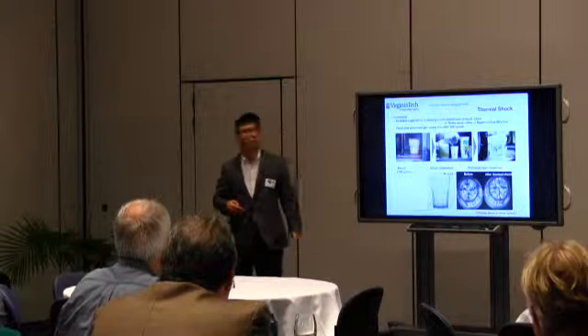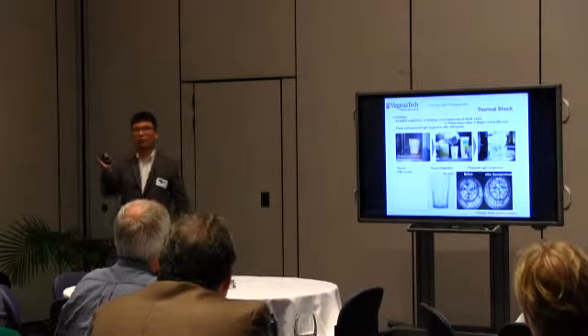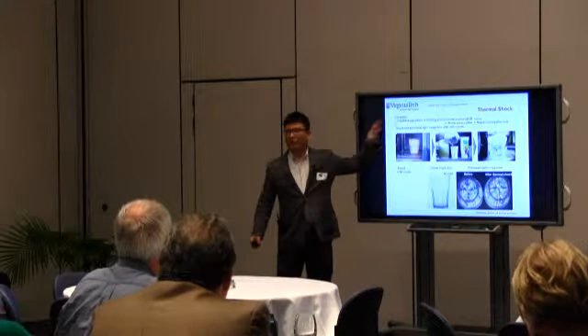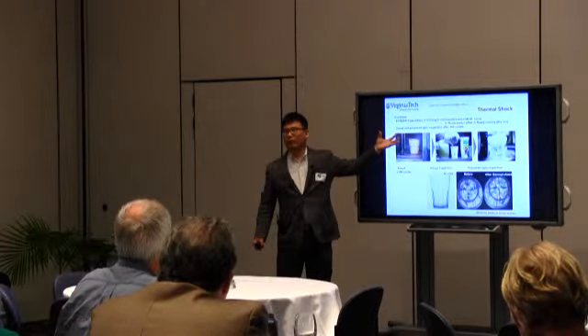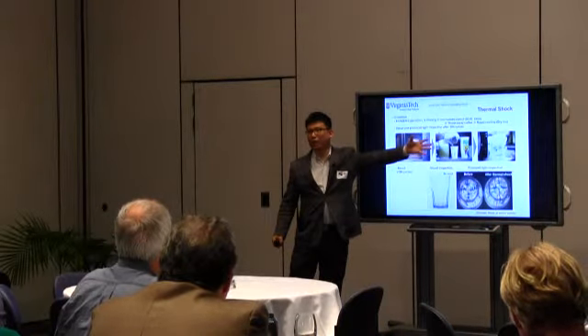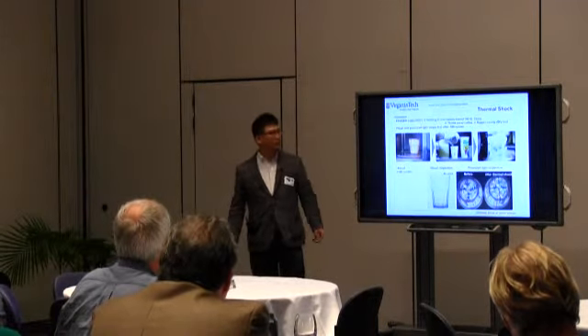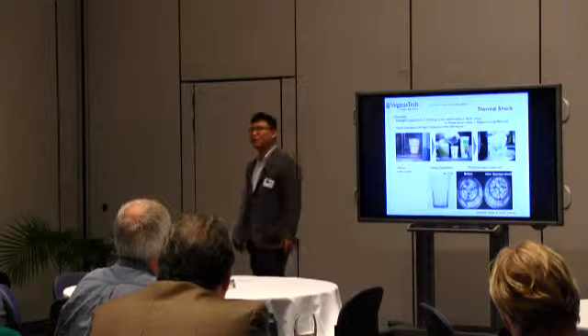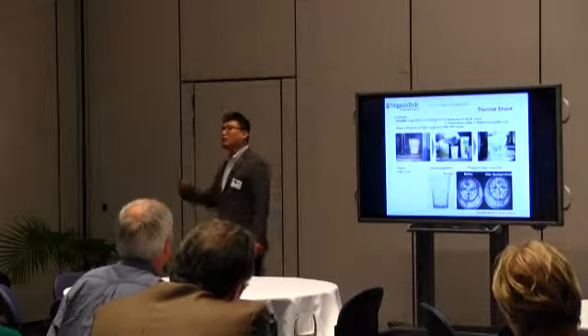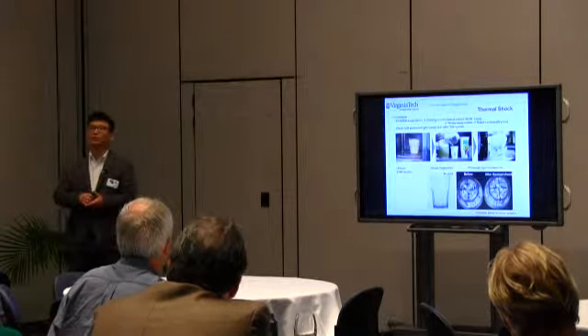Also, we checked the thermal shock. We applied our material for the microwave system. We used the same cup which I showed you. This cup. After using the microwave, this is the coffee. Then we cooled it down quickly. Then we tracked the visual change and did polarized light inspection. There is little change, but it wasn't significant. If you look at the polypropylene product, there's a big change before and after microwave treatment.